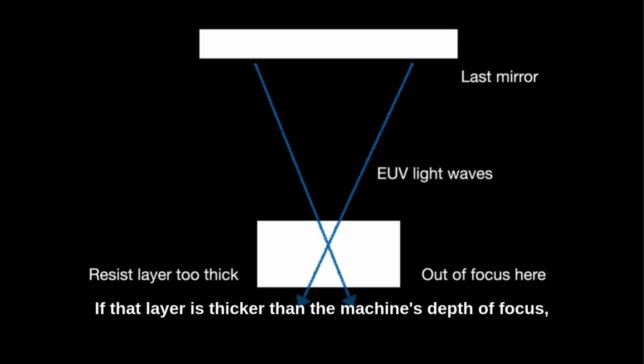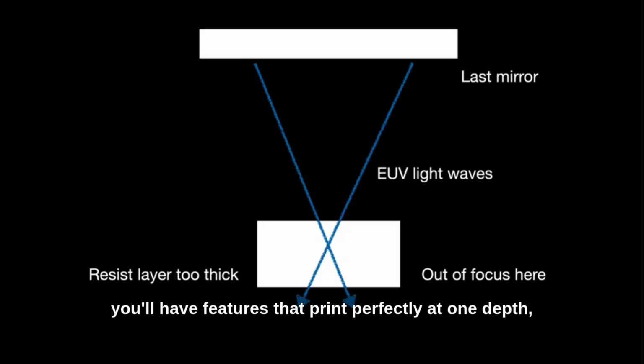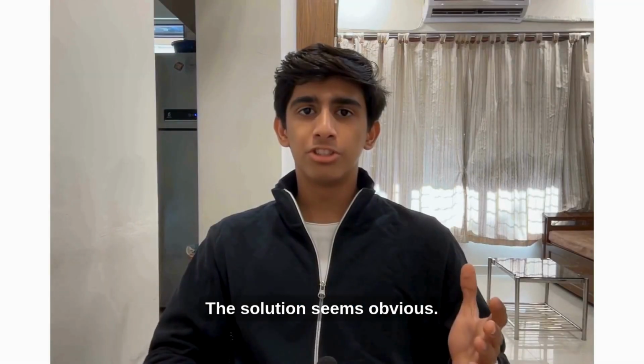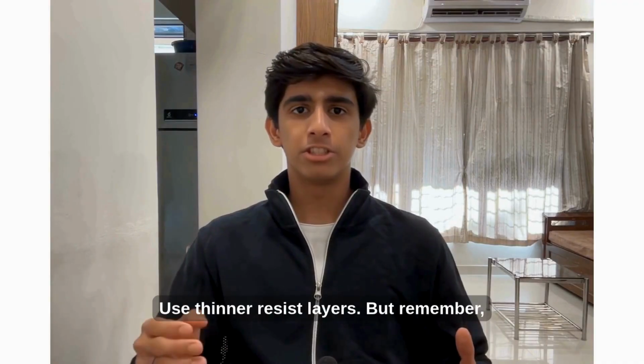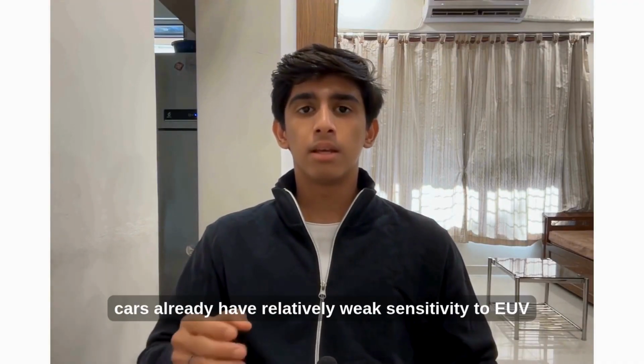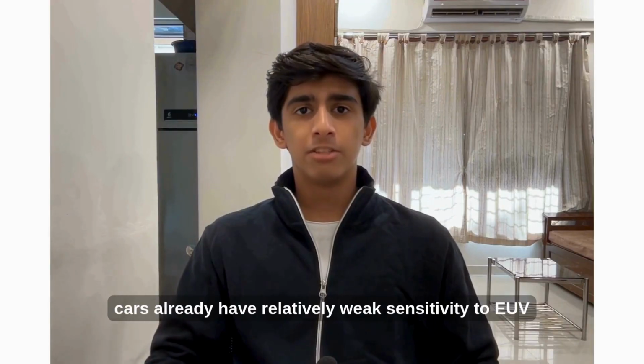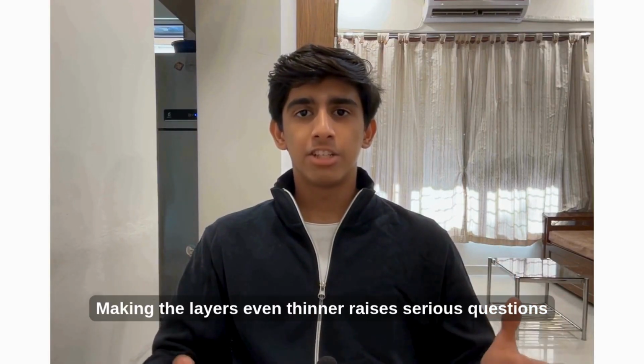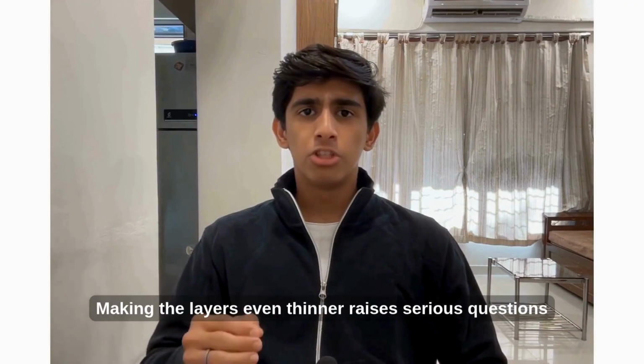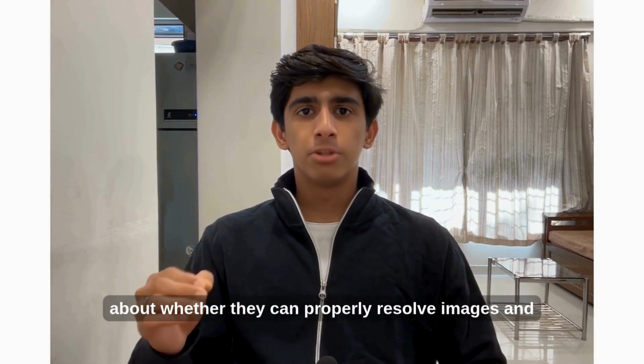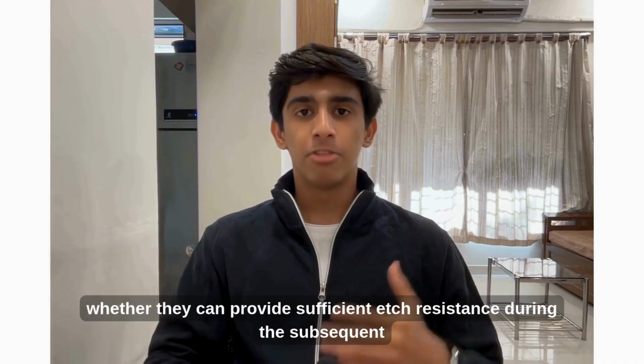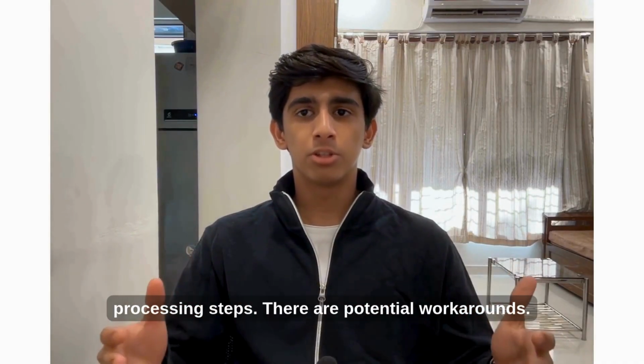If that layer is thicker than the machine's depth of focus, you'll have features that print perfectly at one depth but are completely out of focus at another depth. The solution seems obvious. Use thinner resist layers. But remember, CARs already have relatively weak sensitivity to EUV light. Making the layers even thinner raises serious questions about whether they can properly resolve images and whether they can provide sufficient etch resistance during the subsequent processing steps.